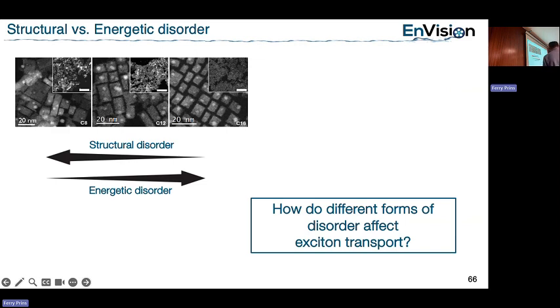Yeah. So what we see, to answer your last question first: even though there is some anisotropy in the shape, that anisotropy, if you look at a larger scale, is random. So that should not lead to a very distinct one-dimensional behavior. We also measure in different directions and you don't see such things. That is the first thing. The first question: does structural disorder lead to anomalous diffusion? Only in very extreme cases.